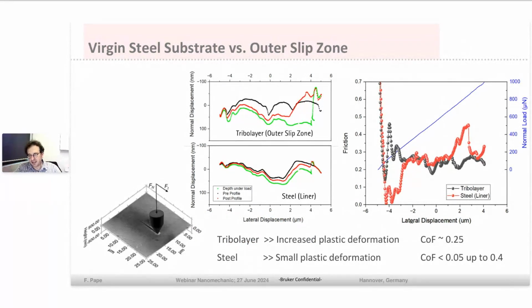What is also very worthy is that we can achieve the frictional properties during plowing into the substrate, that's shown on the right. And the black curve is for the tribo-layer. So here we achieve a more or less stable coefficient of friction of approximately 0.25, while for scratching in the steel substrate, we have a coefficient of friction from 0.05 at the start to 0.4 for the plowing into the steel. So this is quite interesting to have that data. And later on, I will have a slide to show that we are proceeding here.